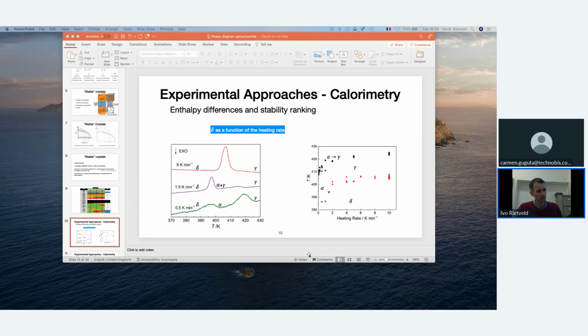Here you have the heating rate, going up in heating rate. You have the temperature here. What you can see is that at the very low heating rates, you see this double peak over here and over here. If you go slightly faster, then the purple point coincides with this one, you see it lower. And at even higher heating rates, you have the immediate conversion of delta into gamma.